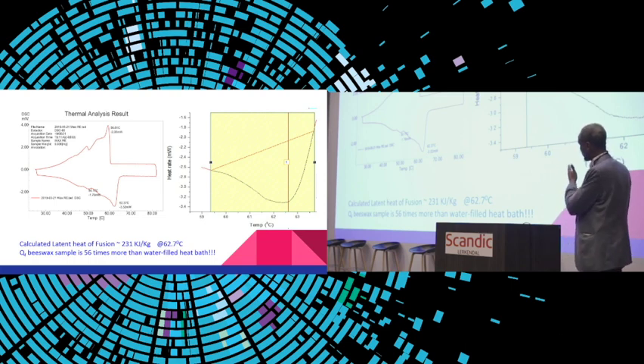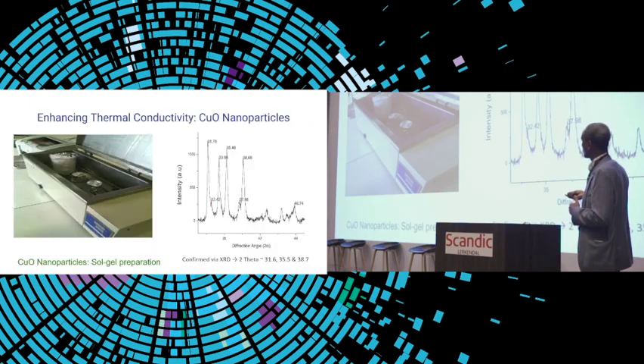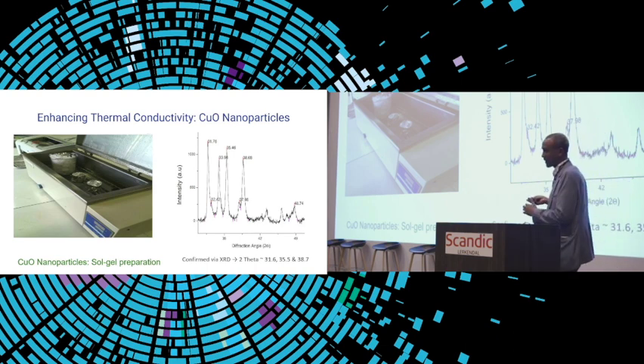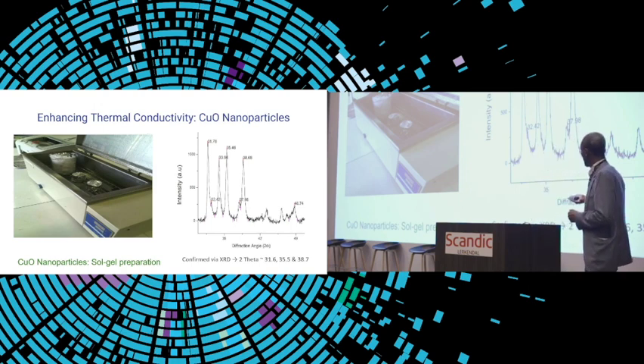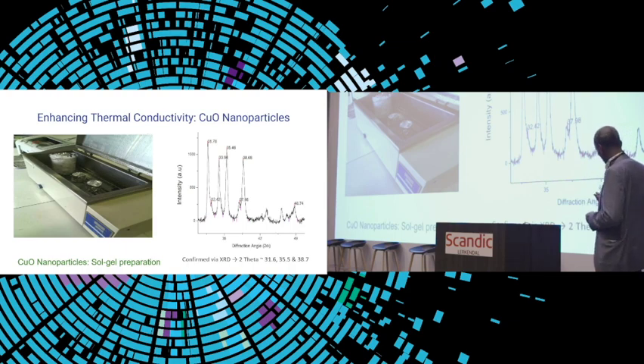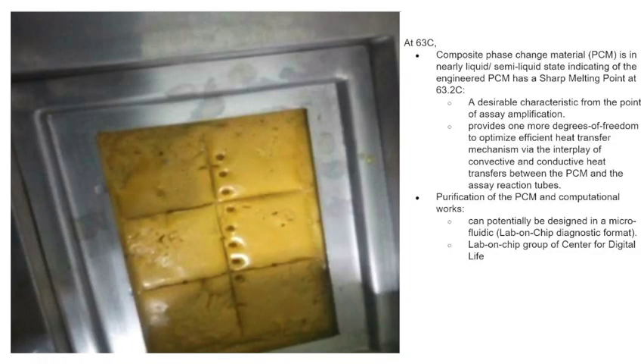So we want to take advantage of this huge latent heat of fusion, and to increase its thermal conductivity, we make copper oxide nanoparticles using sol-gel preparation, which is a very facile method. We confirmed it through X-ray diffraction, especially the 35, 31 and 38 peaks, which are indicative of copper oxide nanoparticles. So we blended it with beeswax.